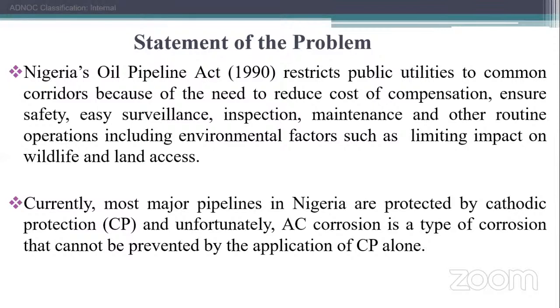And in Nigeria, or not even only in Nigeria, primarily to protect a pipeline, the first and basic thing to do is to coat the pipeline. But as the process entails, no matter how you do your coating, there must be discontinuities. On the technical side, we call them holidays. The coating going on holiday means there is a defect, a discontinuity in the coating. So discontinuities must exist, no matter how tiny.